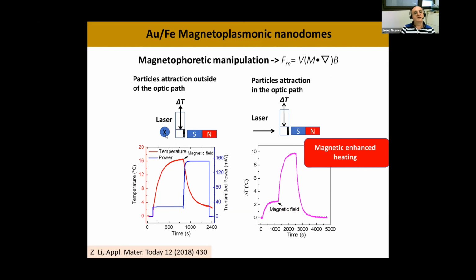Here, in this case, the laser is pointing towards the screen, and we have the magnet on the side. So when we put the magnet, what we basically do is to remove the nanoparticles from the laser path. And what this does, that when we apply the laser without magnet, it starts heating. And now we apply the magnet, the particles go away from the laser path, so then they don't heat anymore. And here you see the transmission increases very much.